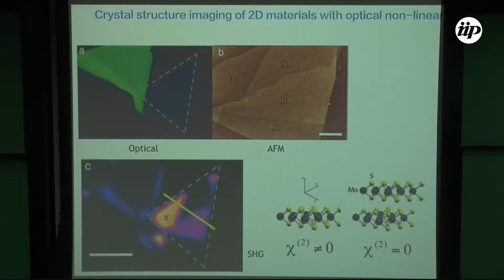Okay, so back in 2013, we did this experiment. We exfoliated MoS2 on a silicon dioxide substrate. This is the AFM image. Here it is showing the monolayer MoS2, 2 layers, 3 layers, and 2 layers.